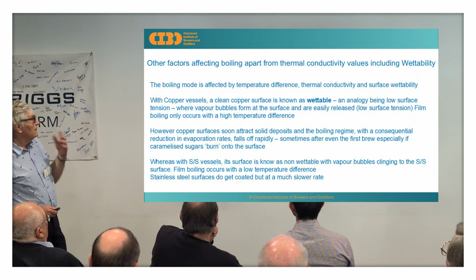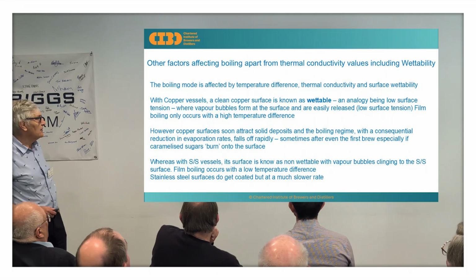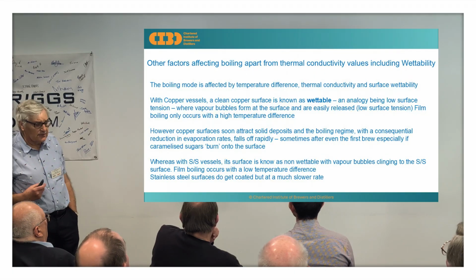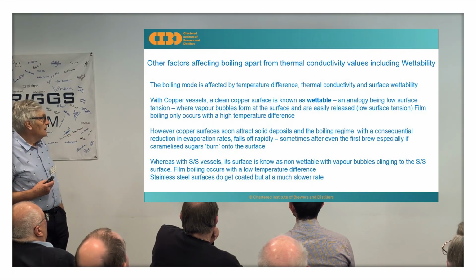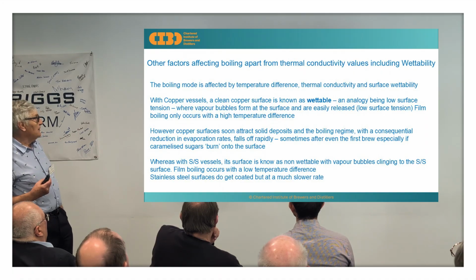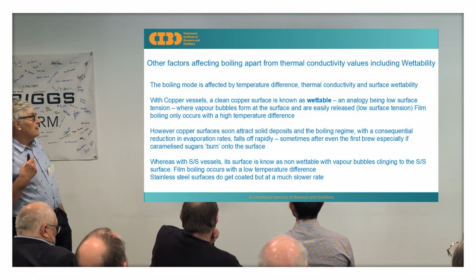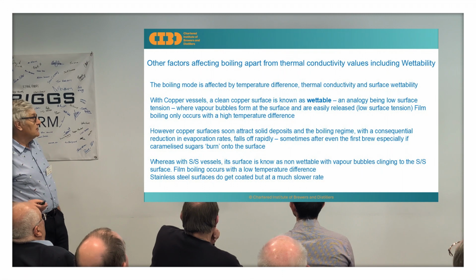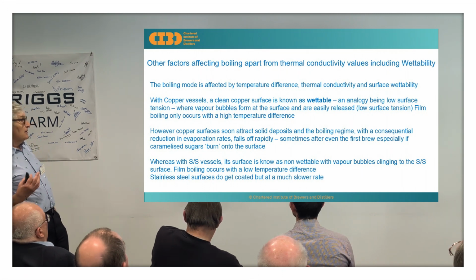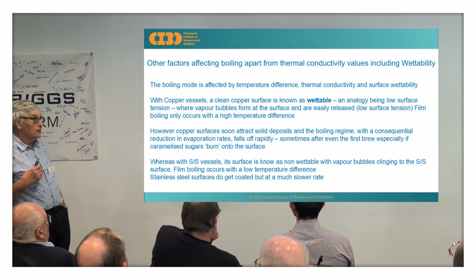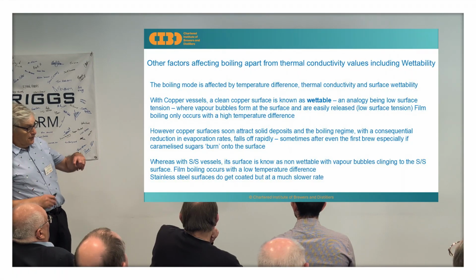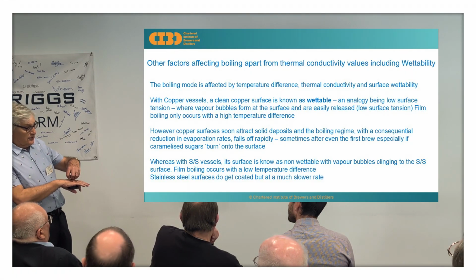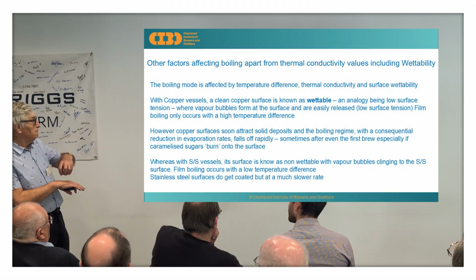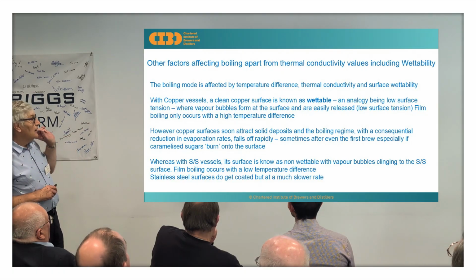There are other elements associated with thermal conductivity, and this is an element called wettability. The boiling mode is affected by temperature difference, thermal conductivity, and surface wettability. With copper vessels, a clean copper surface is known as wettable, and the analogy of this is low surface tension, where the bubble forms on the surface, and it doesn't take much energy for that bubble to rise to the surface.